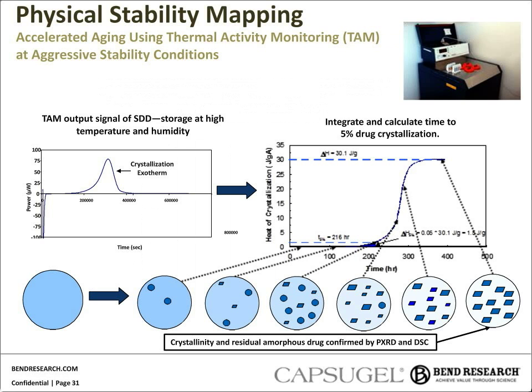As we advance a compound along, we'll get into some more sophisticated physical stability mapping. And in this case, on this slide, we're describing using isothermal calorimetry to actually measure crystallization kinetics. And so schematically here, we're going to put the samples up at accelerated conditions where the temperature's at or even above the glass transition temperature of your dispersion, and then watch the heat flow as these systems phase separate and then crystallize out.